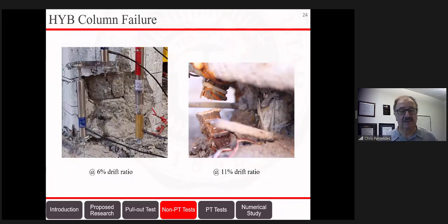So as far as how did failure start, in the hybrid column that you see here, at about 6% drift, we started seeing spalling for the first 250 millimeters of height, the first 10 inches. And this exposed the outer layer of the fiberglass spirals that you can see in this picture. This happened at around 6%, which is still a very large drift. And then at 11%, we saw that a fiberglass longitudinal bar fractured. You can see it here in this picture. This is where it fractured.